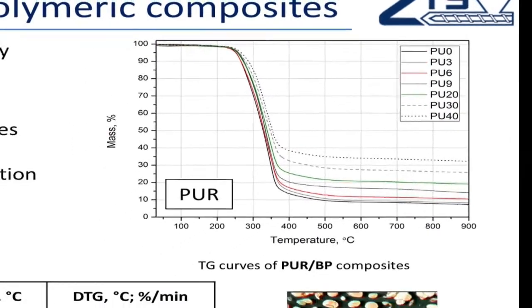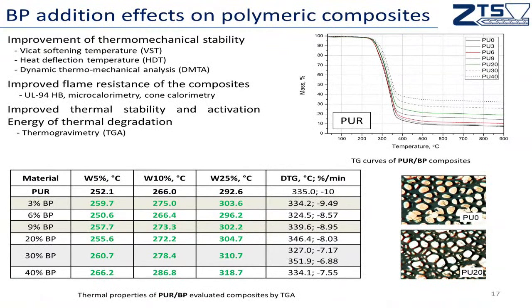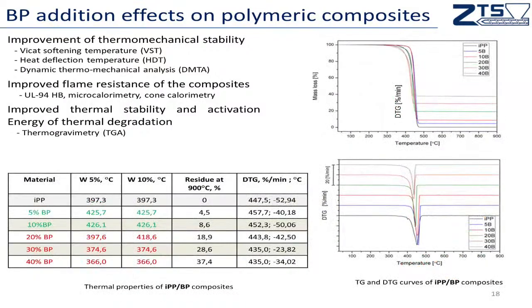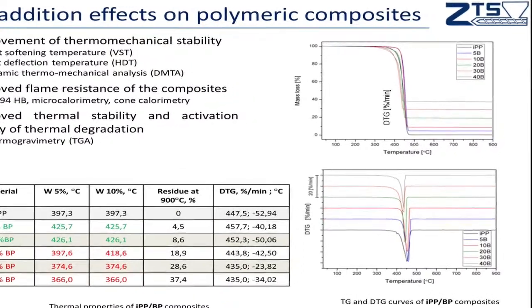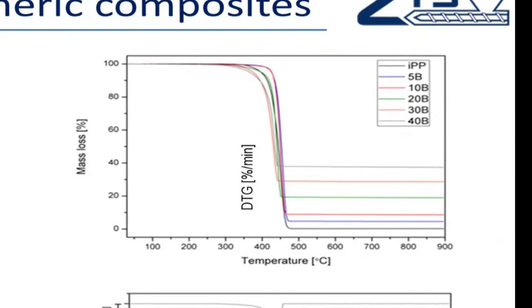So also we can use this material as a safe thermal isolation material. When we move to the next slide, unfortunately, we can see also that not for all materials these benefits can be achieved. For some materials, such as isotactic polypropylene, we can see that the agglomeration of the filler occurred, and in fact the particles came into mutual contact, and the thermal conductivity of the material was increased, and therefore also for more than 20% of the filler, the thermal stability was decreased in comparison to pure material.